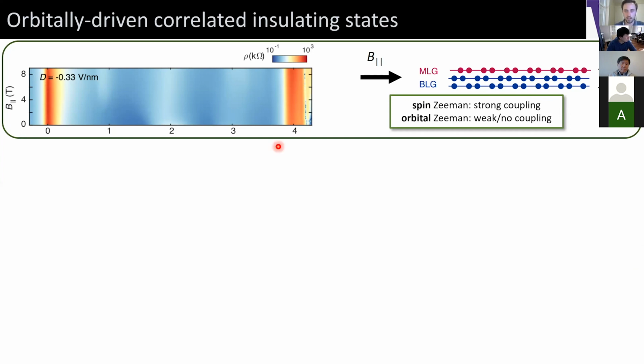And the in-plane magnetic field should couple to the spin Zeeman because spin doesn't care about the direction of the field, but it should not couple to the orbital Zeeman, or at least not strongly, because it's roughly a 2D sheet. So there's not a strong orbital component out of plane, or in plane, sorry. And when we measure the device resistivity with an in-plane field, we see that really not much happens. So that's suggestive that we don't have strong Zeeman effect of these insulating states.